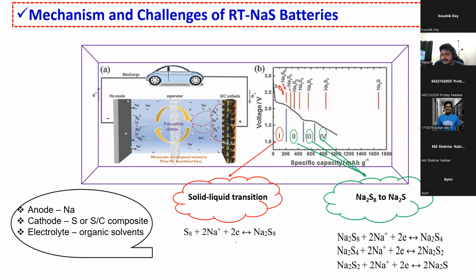S8 will react with the sodium and the electrons to form Na2S8. This will have a capacity of 200. And when we drive the reaction from Na2S8 to Na2S6, Na2S4, Na2S2 and Na2S, we will get the maximum capacity out of it. So the idea to take from this plot is that to get the maximum capacity from the sodium sulfur battery, you have to drive the reaction to the complete end. That means you have to drive the reaction to the formation of Na2S. Only after the formation of Na2S will you get the complete capacity out of this battery.